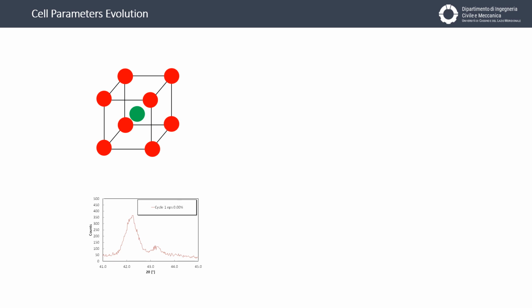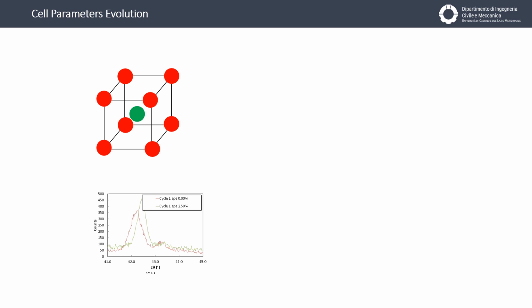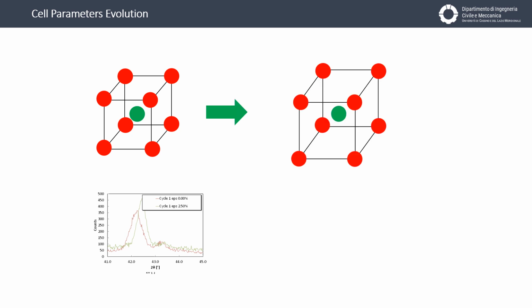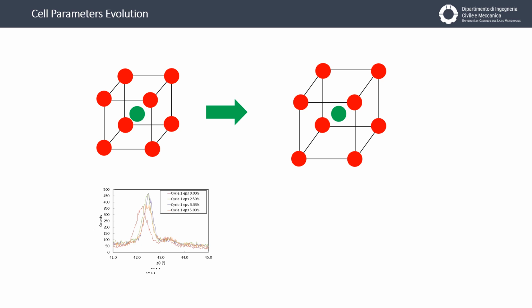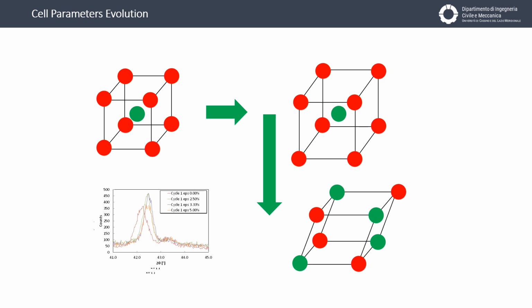Considering all the tensile steps, we can see that in the first spectrum we can calculate the cell parameter of a cubic cell. Using the initial deformation step, 2.5%, we can see that the position of peaks changes in terms of diffraction angles. And it means that we have cubic centered cells, but the dimensions are changed, are increased. Then we have a presence of the peak of the martensite. It means that we have a presence of the monoclinic cell. In order to calculate the variation of cell parameter, we can see that from the first spectrum, the cell parameter is around